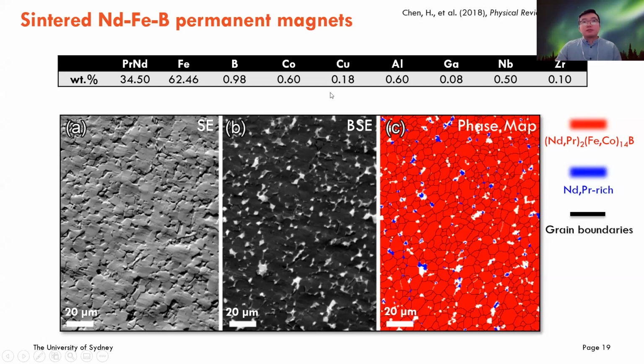For the sintered Neodymium Iron Boron permanent magnets, you can see the structure looks similar to this, and the magnet is composed of mainly two phases. One is the gray part here, called the matrix phase, which is the 2-14-1 phase, and the brighter phase is the rare earth rich phase, and also some grain boundaries highlighted by the black lines. The coercivity in this type of permanent magnet is basically determined by nucleation on defects, especially the defects at the interface between these two phases, and also on the grain boundaries here.